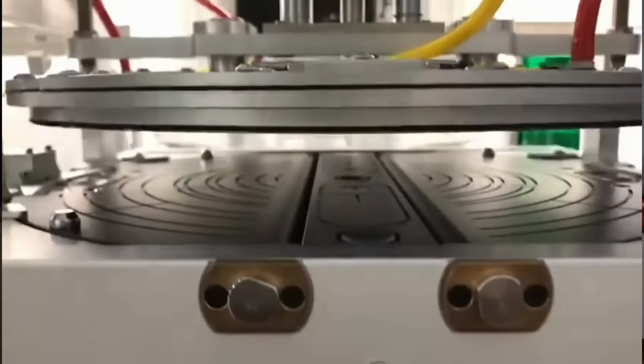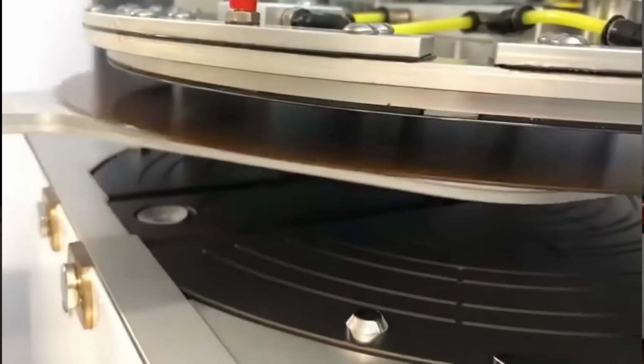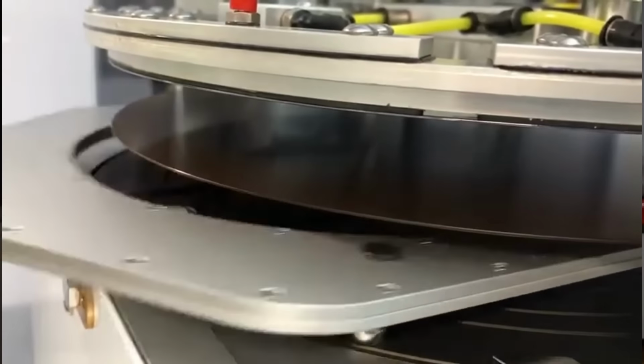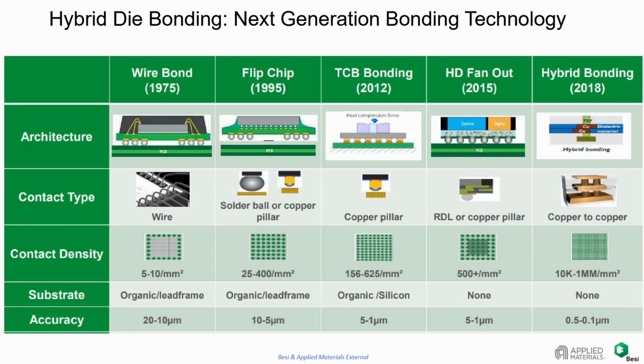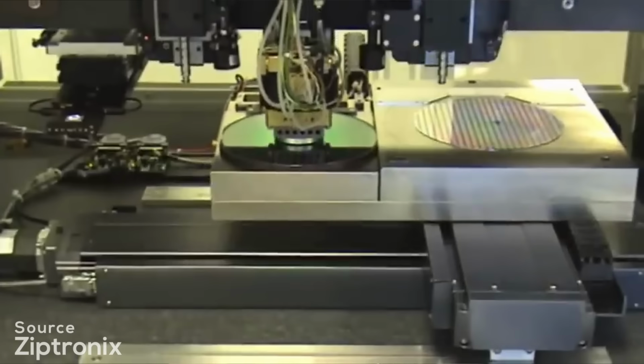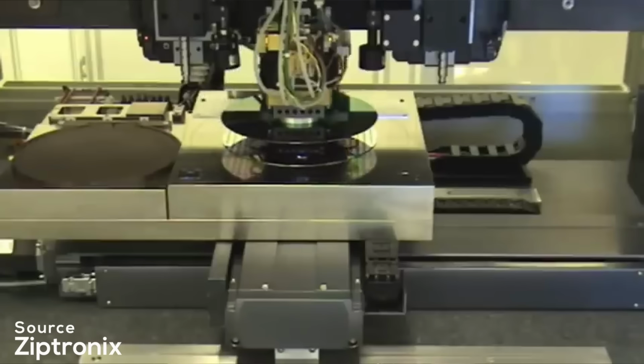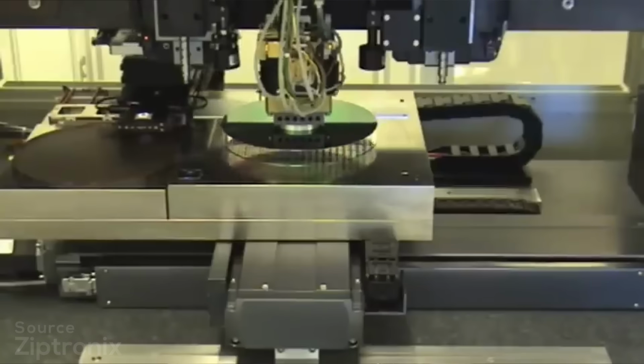Direct copper-to-copper connections offer a couple of advantages. First, they can be much smaller than even the smallest of solder-based microbumps, increasing the interconnect density. There are no solder-related problems, no deforming. The placement of each copper pad is tightly controlled and they are fully isolated by the dielectric material surrounding them. That means you can place them much closer to each other. The main advantage of a higher interconnect density is an increase in energy efficiency.